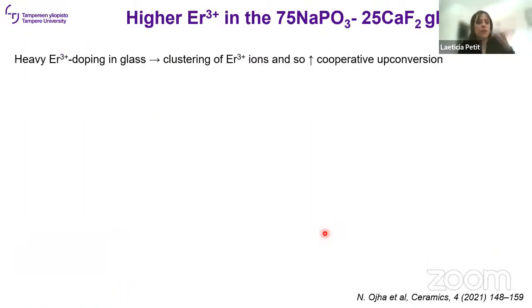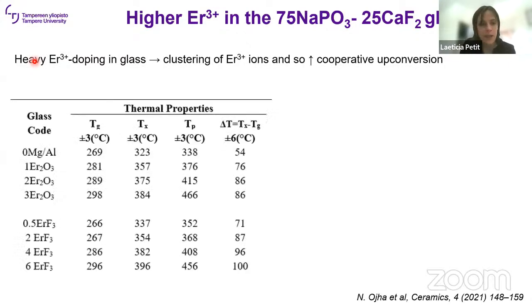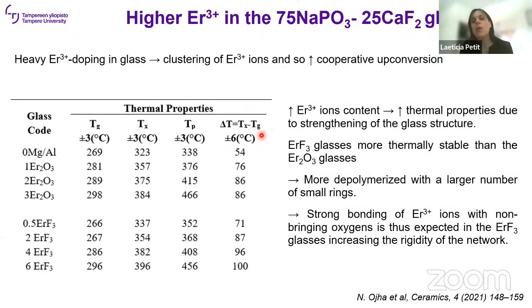So what we try to do is to increase the thermal stability of the glass, so we try to first work on that. We added a larger amount of erbium, so we try to have this clustering of erbium ions, and then we can further increase the upconversion property. So here are the glasses that we prepared very recently. We use 2 different erbium precursors, erbium oxide and erbium fluoride. And you have here all the thermal properties, and especially the delta T. When you increase the erbium content, you increase the thermal stability, and this is due to the strengthening of the glass structure. And the erbium fluoride glass is actually more stable than the erbium oxide one. So for the moment, that is the one we are most interested in.